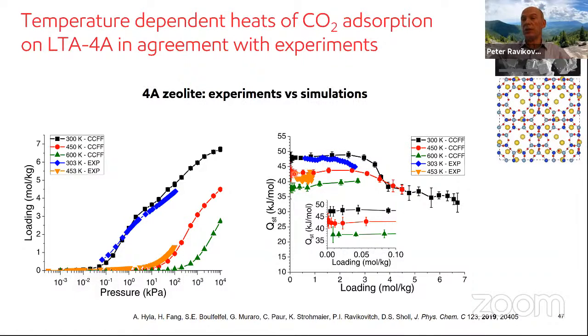And what you see immediately is that there is a strong temperature dependence. So at 300 K, then at 450, and then 600 K, there is a quite substantial temperature dependence of the heat of adsorption. And this dependence is confirmed experimentally. This is not what you would expect, because I just showed you an example of 13X zeolite, where in a sufficiently wide range of temperatures, the heats of adsorption were temperature independent and the isosteres were perfectly linear. So we did very extensive checking.